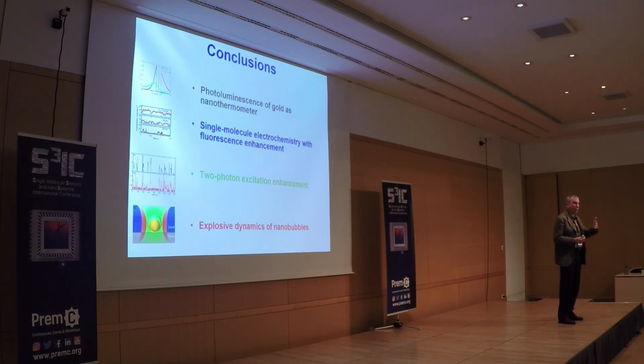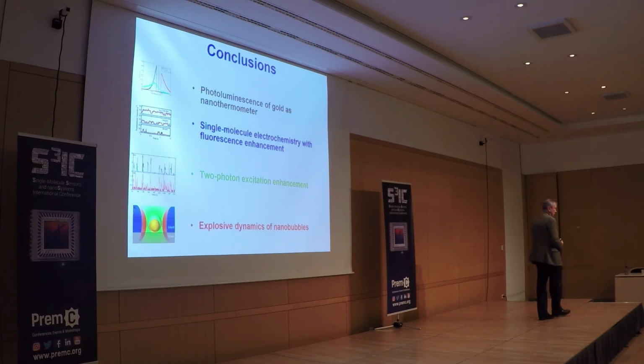And the oscillator strength, if you like, is just the same for all the states. So the same level absorbing, but with different radiative quantum. Okay, I see. And those are the two extremes. And the simulation, and the results that we measure are just between these two simulations. So, which means that very probably we don't have the right parameters, but we would be able to simulate our results by adding more adjustable parameters that we don't know. Okay, thank you.